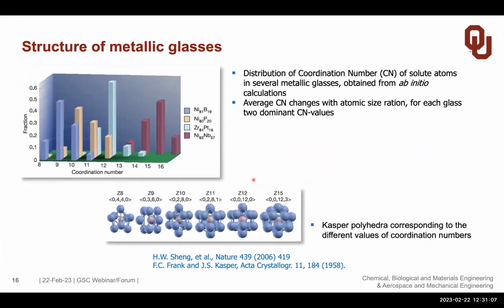Once you have these atomic arrangements in your computer, you can look at what kind of arrangements you find. And here, for different metallic glass classes, so this would be metal-metal, metal-metalloid, or other classes, you see that the coordination numbers which you find dominating are different. But you can find what are called Kasper polyhedra, which correspond to the different numbers of coordination you have around a central atom. And you can give a certain nomenclature to it, and you see that a metallic glass doesn't have a well-defined unit cell like a crystalline material, where we have either FCC, BCC, or other unit cells, but it has a distribution of polyhedra which you assemble together to build this amorphous structure.